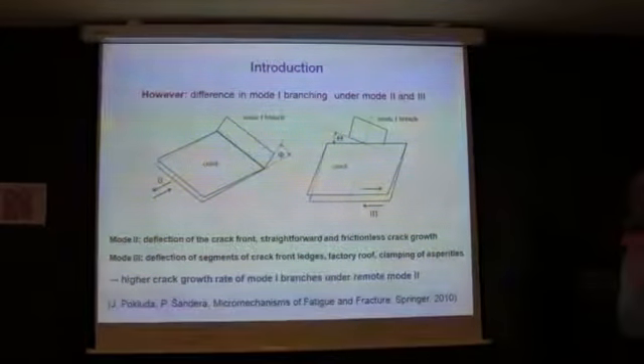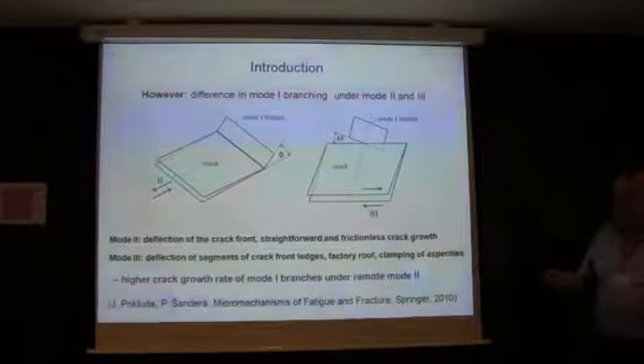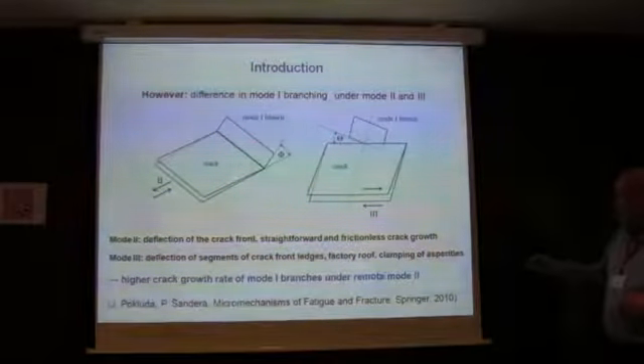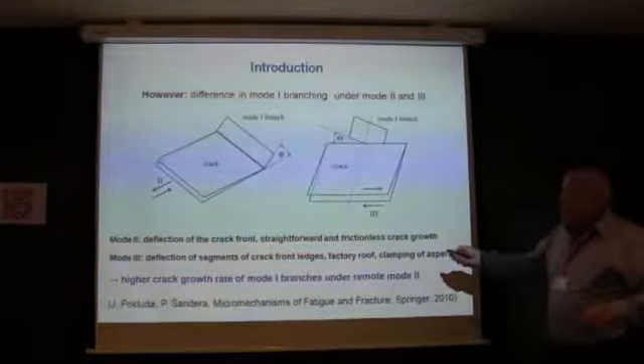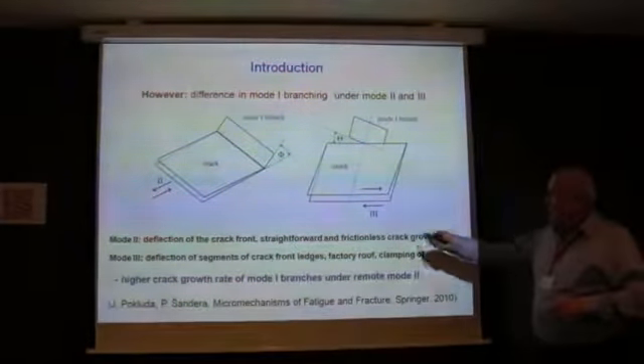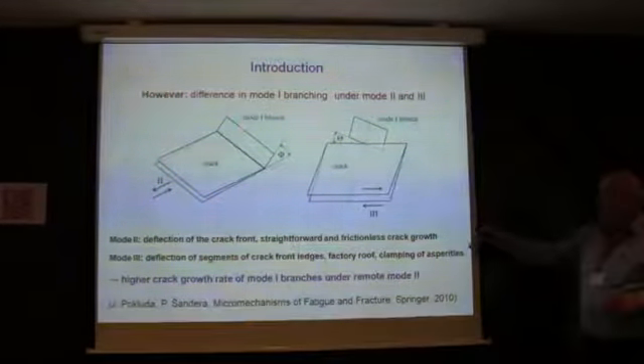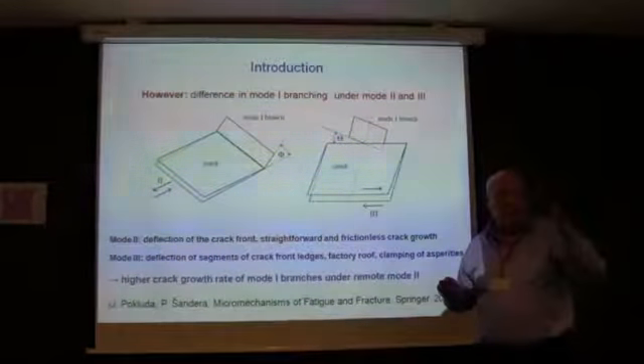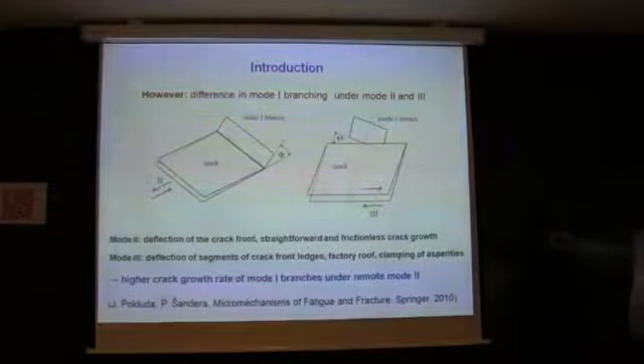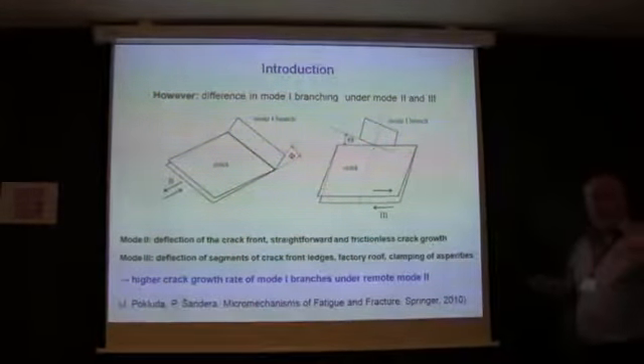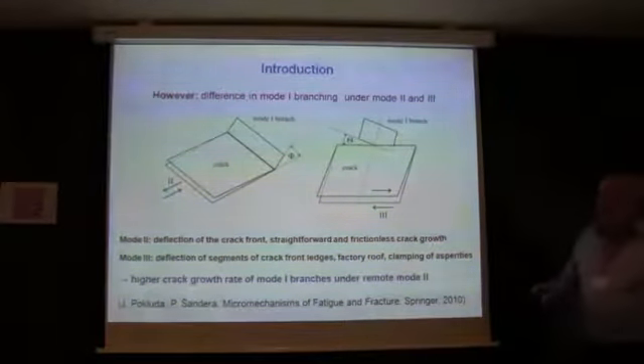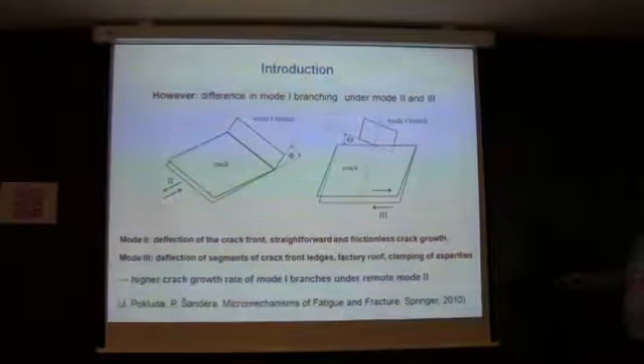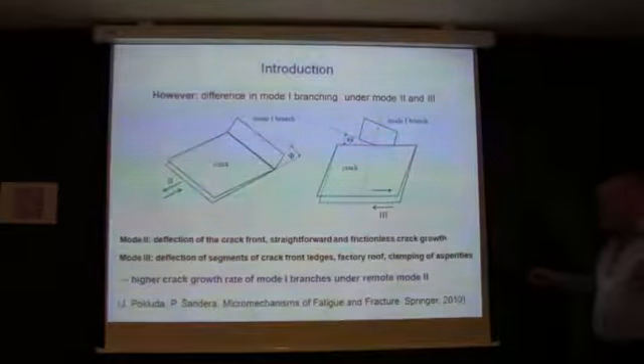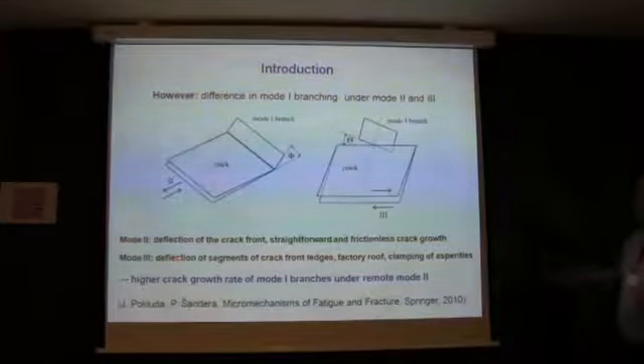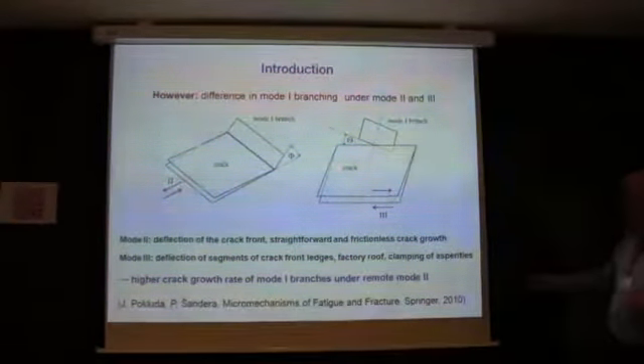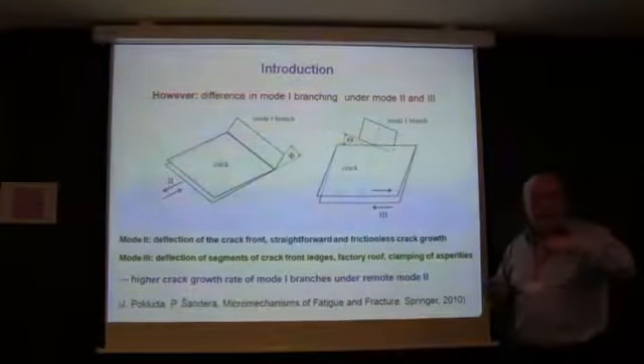Now, there is a geometrical difference between these two modes. If you have just mode 2, like this, in the ideal case, the crack can deflect like this, and you get a common line between the crack and the branch, so it is not so difficult for the crack to deviate to mode 1. In mode 2, deflection of the crack is rather straightforward, and you can then get a shear-frictionless crack growth in mode 1. But in the mode 3 case, you actually have to twist the crack to get the mode 1 branch. This is more difficult because there is only one point here. In fact, it happens on the ledges of the crack.